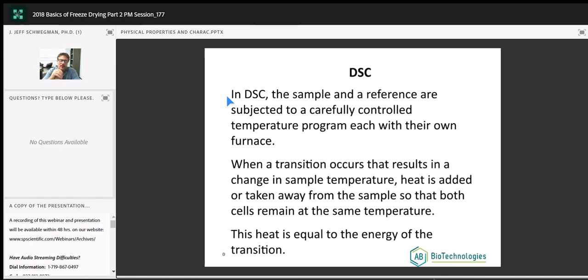What does that mean? The DSC, as we cool down and heat up, keeps the sample and the reference at the same temperature the whole time. So what happens is we cool down, and say the sample pan or the sample nucleates and crystallizes, there's going to be a burst of heat given off. Well, basically, the DSC will equalize the temperature, so it supplies energy or takes energy away from the reference pan to keep them at the same temperature. So now we're not measuring delta T, we're measuring the energy that's required to keep those two pans at the same temperature.